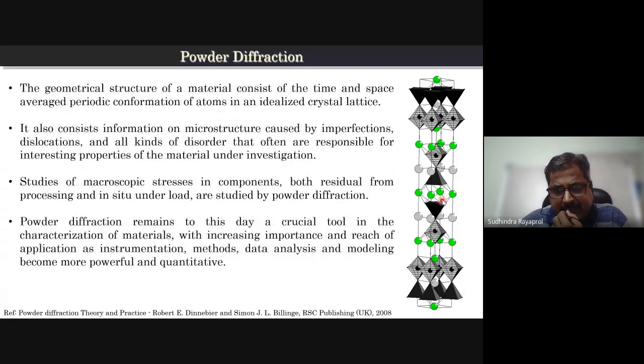The crystal structure generally consists of the information of a material, like atomic positions and what type of atomic species are present at what distances and in what time. It is basically the time and space average of the periodic configuration of atoms. It also consists of information about microstructure, which is caused by imperfections, dislocations, and all kinds of disorder. Studies of microscopic stresses in compounds, both residual and from sample preparation, can be done using powder diffraction.